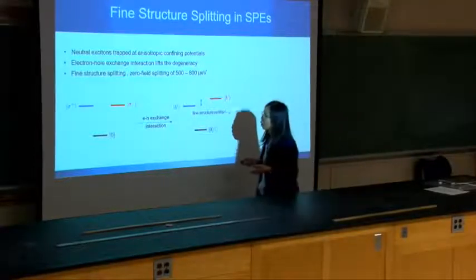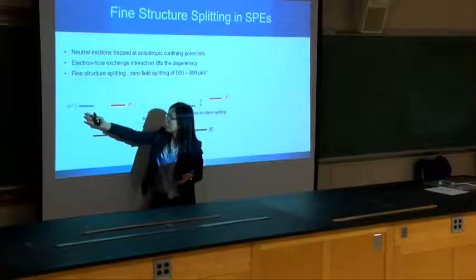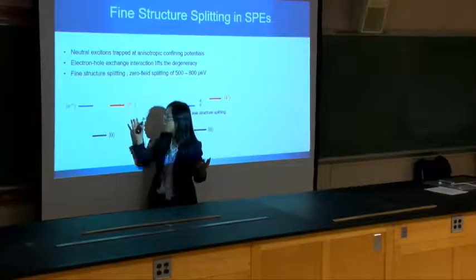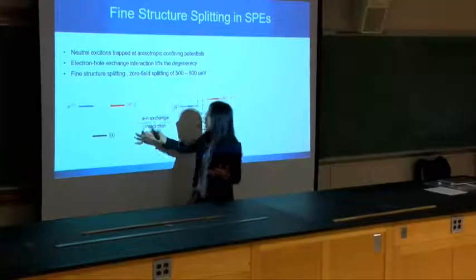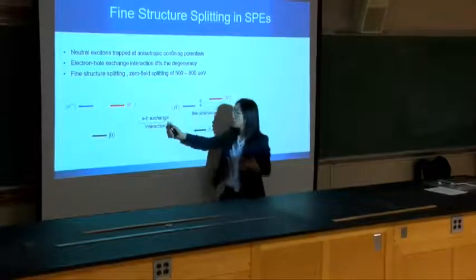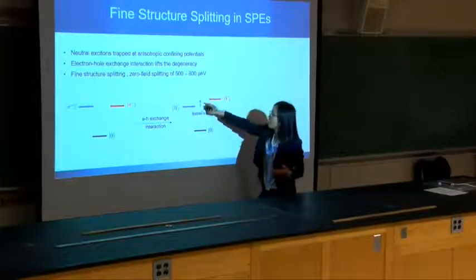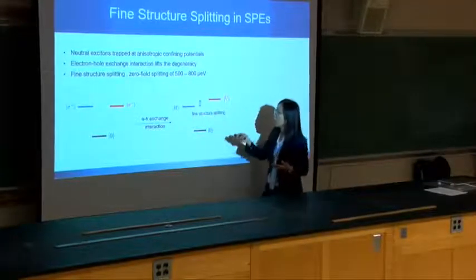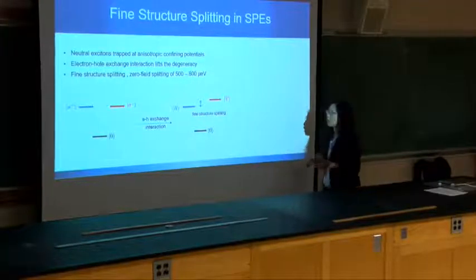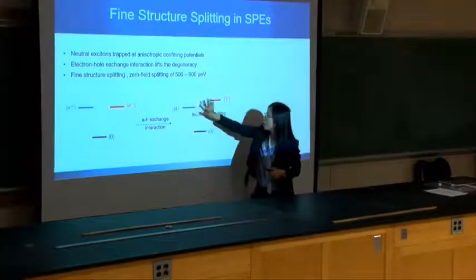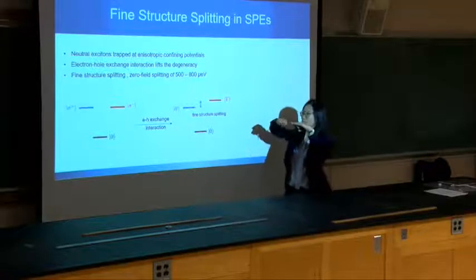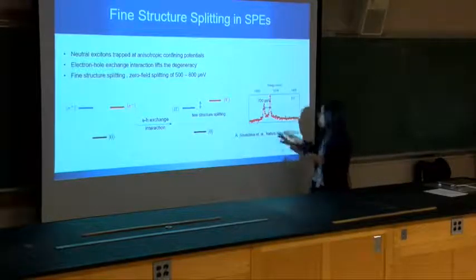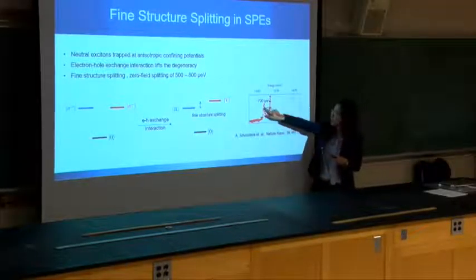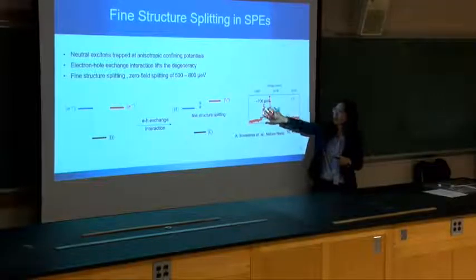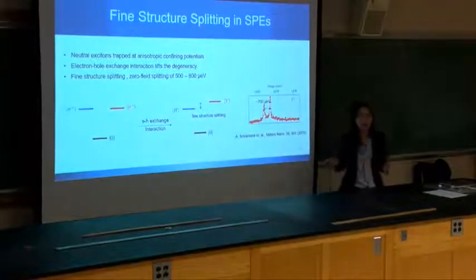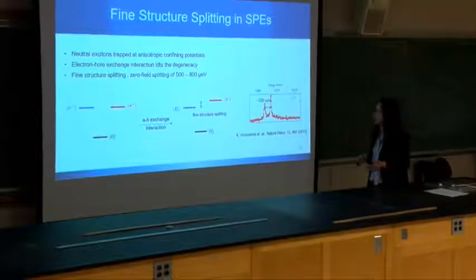So we start from the degenerate states, sigma plus and sigma minus, from the K and minus K valleys. Due to the exchange interaction, we will have a splitting here that we call fine structure splitting, or zero field splitting. And this splitting lifts the degeneracy. It means that for the degenerate state, you will basically see two peaks here. The splitting value is about 500 to 800 micro electron volts in tungsten diselenide.